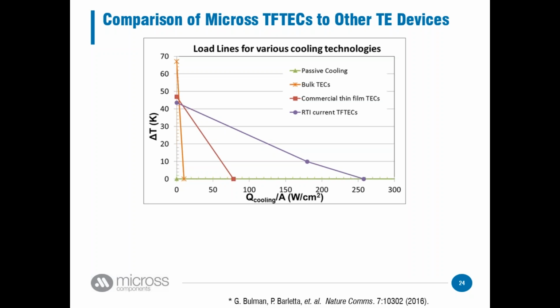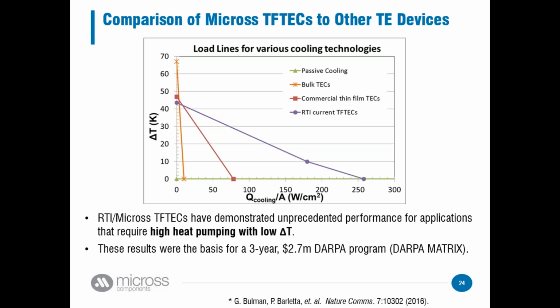Well, you can kind of see here. This is essentially a load line. People use this a lot in thermoelectrics to kind of describe your performance. Your bulk thermoelectric cooler is going to be a guy right here. You're going to get a good, we talked around 70 delta T, and that's a nice number, but the heat pumping isn't there. The commercially available thin film, again, you're looking at something like 80 watts per centimeter squared. But our guy is this guy right here. And you can see that load line is way further to the right than anything that anyone else has described before. So what we can do better than anyone else in the world at RTI and now at Micross is to build devices that can have a high heat pumping at a low delta T.